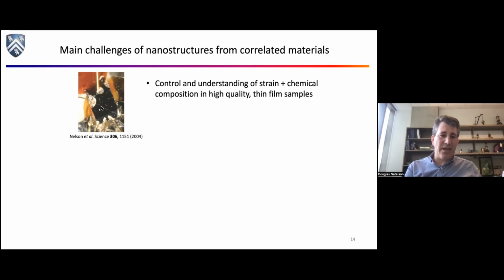It turns out this is strontium ruthenate, another oxide. And the problem is the properties of some of these materials, they change. And you can see someone's just silver epoxied a couple of wires onto this thing, right? If you mess with the chemistry of these things, you change the properties. If you mess with the strain, you change the properties. It's very challenging to get good material.